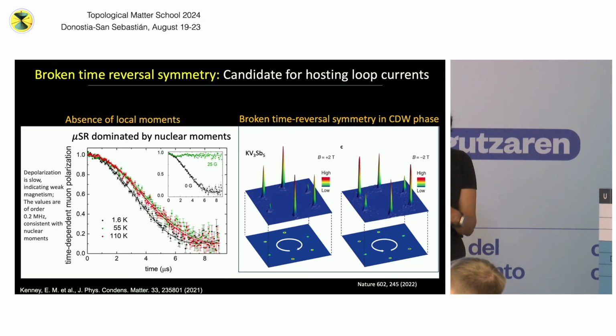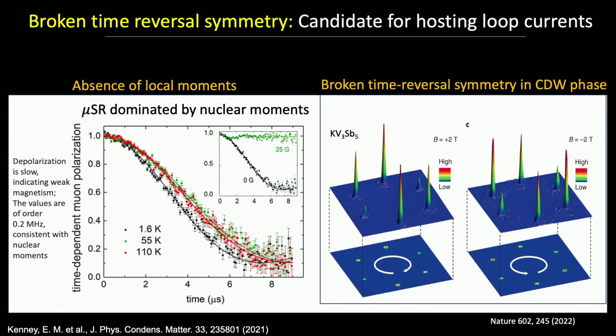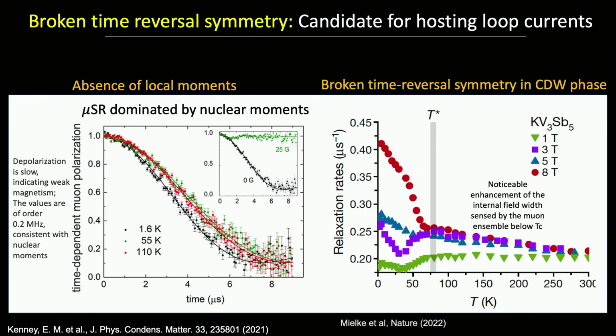So you could manipulate the relative intensity using a magnetic field. So think about what this is saying. You have a charge density wave order. There's no spin associated with it. You take a Fourier transform of a topography. You see the Fourier peaks. First, they should all be the same height. There is no real reason for them to be different heights. So the first question you should ask is, why on earth are they different heights in the first place? And the second thing is, there's no reason they should respond to a magnetic field, right? I mean, why should a charge density wave respond to a magnetic field? It's a neutral object, spin-wise, sorry. So that shows that there's some broken time reversal symmetry.